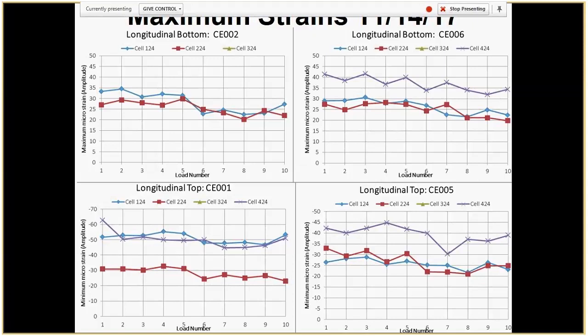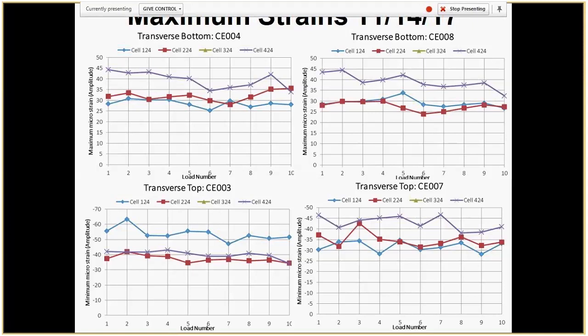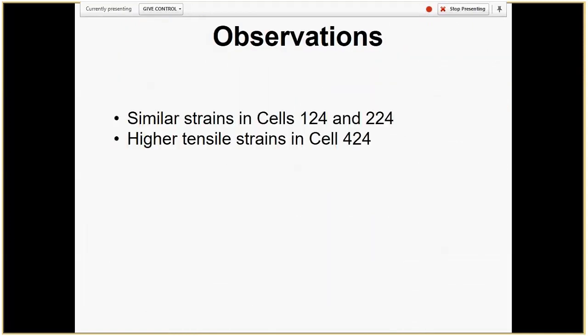We also evaluated data collected in November of 2017, and it's interesting that in this case, cell 124 and 224 showed very similar strain level. Cell 424 actually exhibited higher tensile strains, about 10 microstrain, but still those strains are reasonably low, and of course, as I said, there is no really significant damage. And here we have transverse strains, we have the same trend. So I'd say in this case we have observed a slightly different trend from the previous, but in both cases the strain level is sufficiently low not to create any problems.